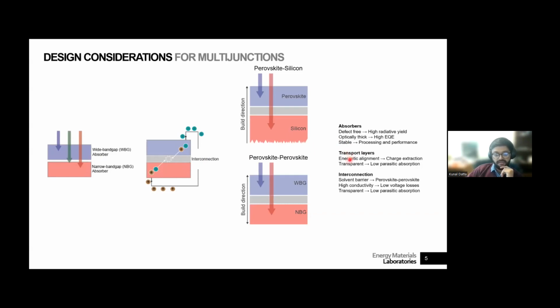Transport layers, you need better energetic alignment. That applies to single junctions as well. That's nothing new. But one thing is that, especially with tandems, you need your transport layers to be as transparent as you can make them, because you're depending on the transmission of these transport layers for the performance of the second cell, and therefore the lower the parasitic absorption can get, the better.